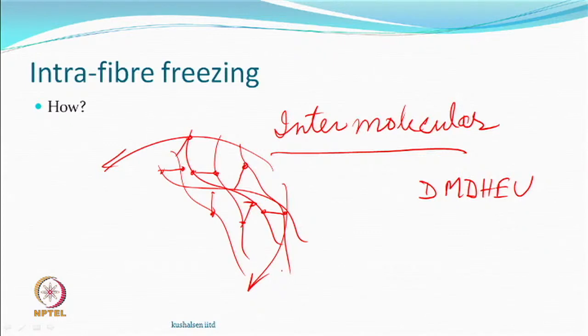So, you deform the material, let us say twist. After this, you do cross linking, you will find that the fiber does not untwist on its own, or it remains in that position because the cross links would not let it go to the other direction, right. But remember, there is no release of energy. If for whatever reason your deformation has put stresses in the fiber, the stresses would remain, okay.